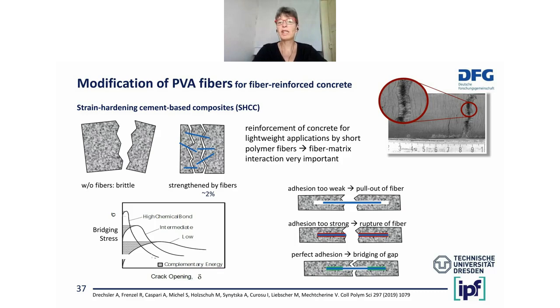Sorry, they are able to bridge the gaps if there are small cracks in the concrete and strengthen the concrete. For this purpose, we need a very well-balanced interaction between the fibers and the concrete. If the adhesion between fibers and concrete is too weak, then the fiber is pulled out and does not have much effect. If the adhesion is too strong, the fiber ruptures and doesn't help very much either. But if we have a perfect adhesion, then the fiber is able to bridge the gaps, and we get many small cracks in the concrete instead of one final failure.